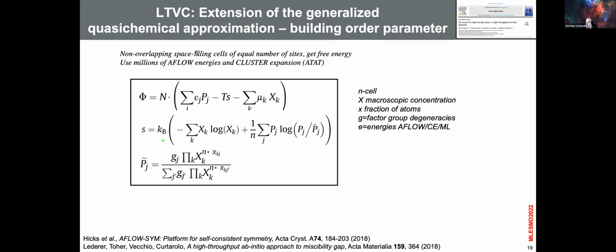Look carefully. You have two concentrations. You have the small x and the big X. The big X is really the big macroscopic composition. I give you 1 million blue atoms and 1 million yellow atoms. That's it. So you're 50-50. But then you shuffle them around and you create small tiles. The small tiles have their own compositions. One can be 60-40, the other can be 33-76, right? Okay, so those are the microscopic compositions and those are the macroscopic. So there are a lot of ways you can distribute the microscopic compositions to get the macroscopic ones. Okay, and all of this is calculated by AFLOW. So you see that you have the microscopic degenerations and then the degeneration of the factor group. So you can get all these various p, and it tells you the weight of that particular configuration.